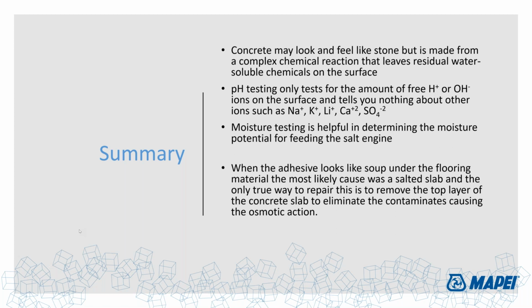Okay, new question. Can we apply polyurethane on new concrete after about a week so we can keep the substrate from dust, which we should remove later before applying the coat? Okay, I guess the question is, can we apply polyurethane on the new concrete after about a week? All right, so generally speaking, urethanes are not going to be affected too much by high pH conditions.